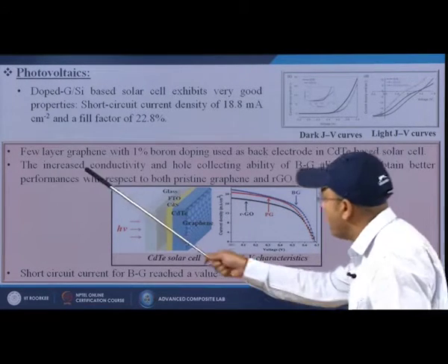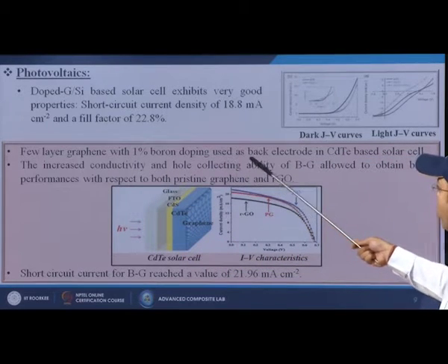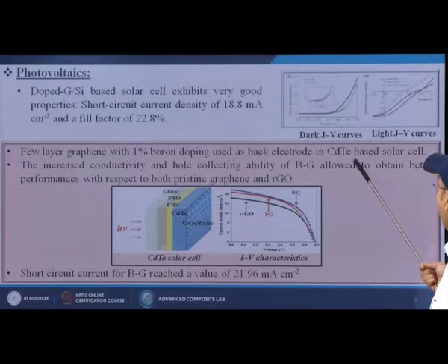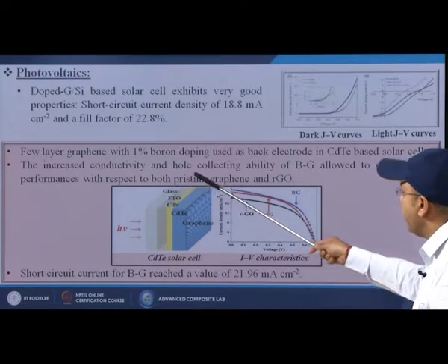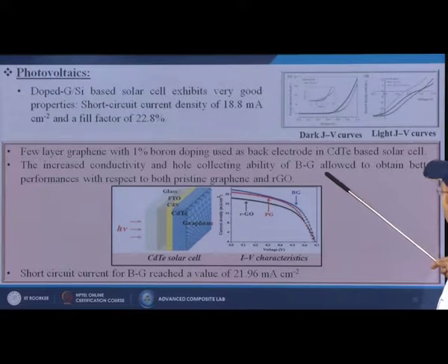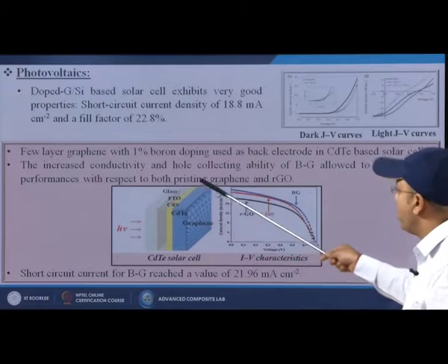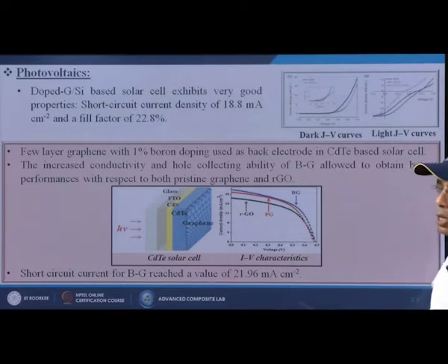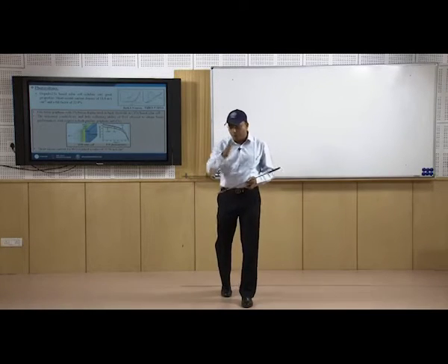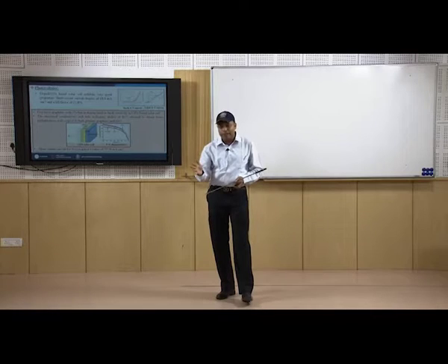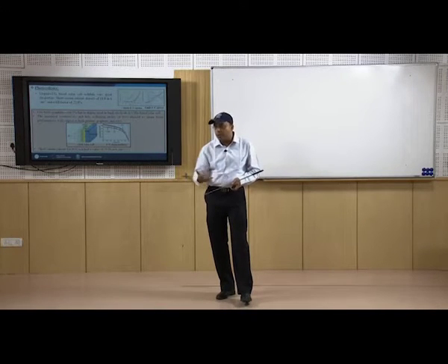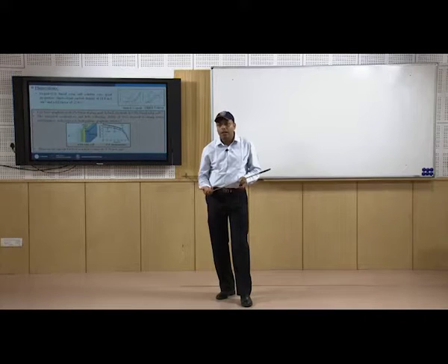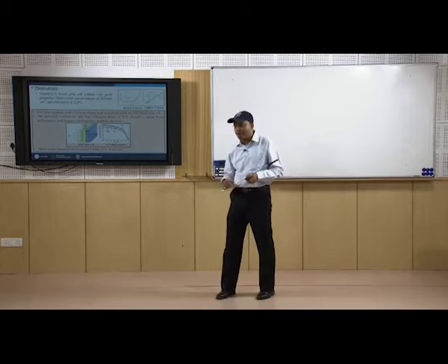Here we are also trying to show that few layer graphene with 1% boron doping was used as a back electrode in cadmium telluride based solar cells. The increased conductivity and hole collecting ability of boron graphene allowed better performance with respect to both pristine graphene and reduced graphene oxide. If you remember, graphene oxide is first made from graphite itself, then when we remove some functional groups from it, that is known as reduced graphene oxide. Graphene is the removal of all functional groups from it, and its layers may be one, two or three layers. That is why it is called few layer graphene sheets.